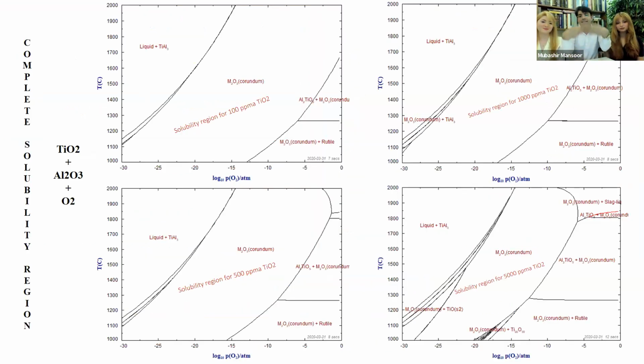Now, if we extend the same diagrams even more, we can actually plot these new diagrams, which are beautiful maps of how we can create complete solubility based on the concentration of rutile we have in sapphire. So what it's basically showing is that you need to have a low oxygen partial pressure. This x-axis here, the -30 means almost no oxygen. 0 means a lot of oxygen. And it means if you have a lot of oxygen in your furnace, to get to this full solubility, to this shaded, wide region, you should have a temperature over 1600 Celsius.